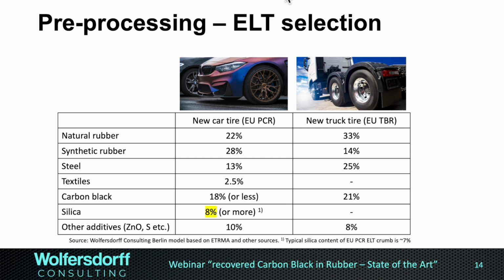This shows you the different composition of car and truck tires. Of course, there are different compositions between summer and winter tires, different types of SUV tires, and performance tires. And the reason I'm showing this is we need to feed the pyrolysis with a consistent composition. So we need to control the tires, and the easy way of doing it is controlling the type of tires. And then it gets a little bit deeper. For example, Black Bear Carbon, the recovered carbon black maker in the Netherlands, has a patent for sorting the tires by measuring the silica content with an XRD, so X-ray diffraction method, in order to really narrow down the compositional feedstock into the pyrolysis to have a very, very consistent recovered carbon black.